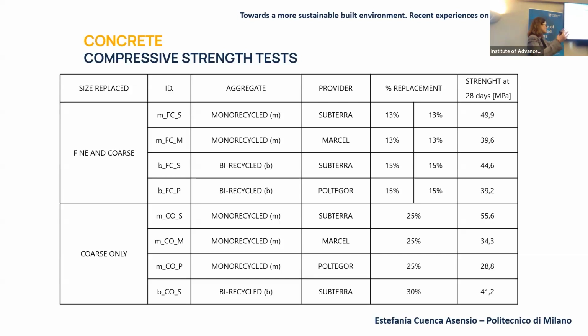And the conclusions that we are going to analyze depend on the providers. It depends if it's mono-recycled or double recycled, so let's move on very quickly. You can see here in the provider column the rate of replacement for each mix. And in the last column, more or less the compressive strength was pretty much the same. Only in this case, we obtained the highest value, for the mono-recycled coarse only from Subterra.